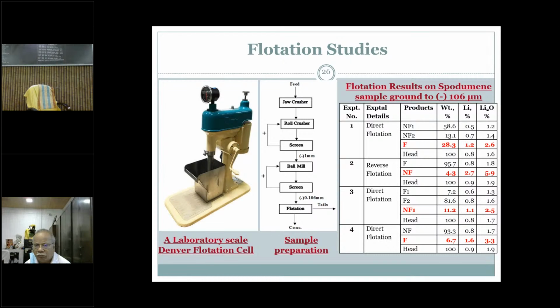And we have carried out a couple of flotation studies. You can see we have done some direct flotation as well as reverse flotation. The direct flotation is the one where the spodumene is concentrated in the froth product, and the reverse flotation is the one where the spodumene is enriched in the non-froth, and the silicates are floated. You can see experiment number 2. The concentrate is enriched in lithium contents above 5%. So flotation and gravity concentration are extensively used, and it shows that it is possible to enrich the lithium content from the Indian deposits.